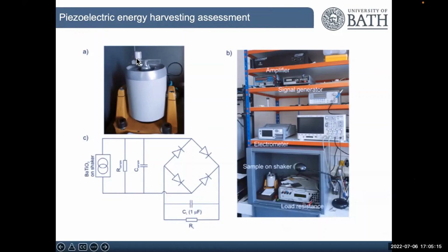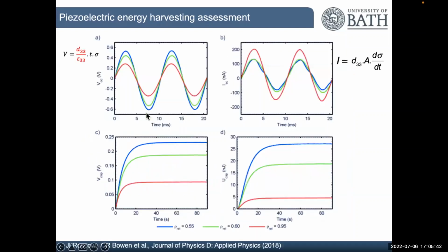So this is a porous material here on a shaker. It's got a mass on top, applying that constant load. And then what we do is we accumulate that charge as we change the polarization and put it onto a storage capacitor. So it could be a supercapacitor, it could be a standard capacitor, and see which wins. Is it the porous material that's generating more energy or generating a higher voltage? And it did work, and that's because the figures of merit do work.